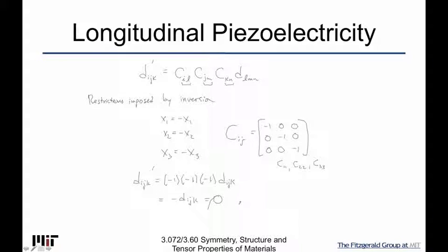So basically, it means that any crystal with inversion means no piezoelectricity. That is very cool because it shows you the power of symmetry arguments. Right here, right now, we could show you that a third rank tensor, and here we're talking about piezoelectricity, but if you have another third rank tensor, inversion will always do this, right? It's because it's 3 minus 1s, right? So inversion, anytime you have a third rank tensor, is not going to be able to have that property. So it's a pretty interesting and fundamental conclusion, right?